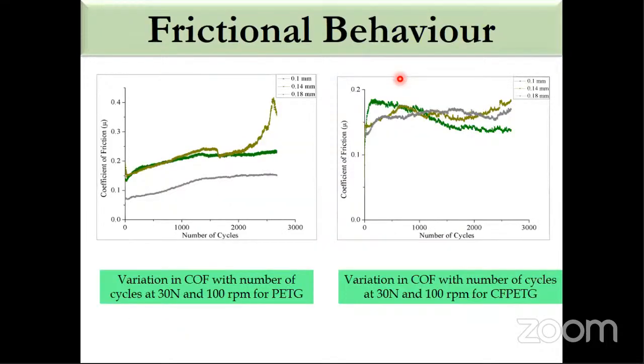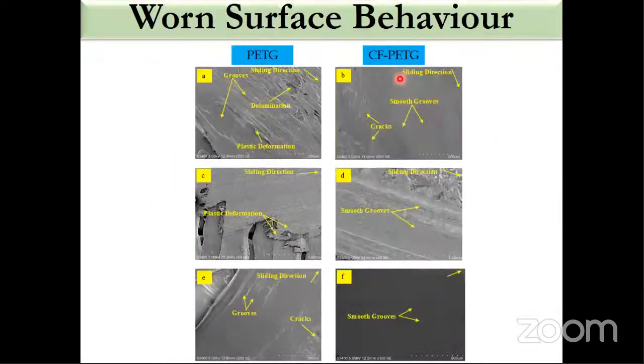From the frictional characteristics, we could observe that for PETG, if you run it for a large number of cycles, the trend is that with the increase in the sliding distance, or with the increase in the number of cycles, the coefficient of friction is increasing, which is not actually a good trend. But when we reinforce it with carbon fiber, the coefficient of friction goes down when we increase the number of cycles up to, say, 2000 or 2500, which is actually due to the layer formation capability of carbon and the solid lubrication capacity of carbon, which is helping in exhibiting this behavior.